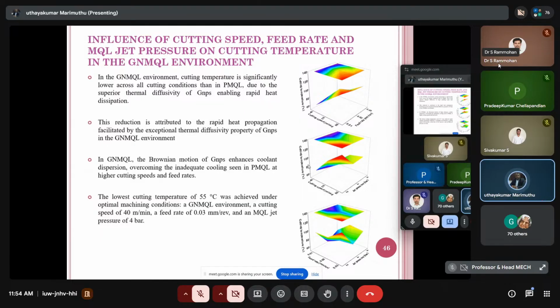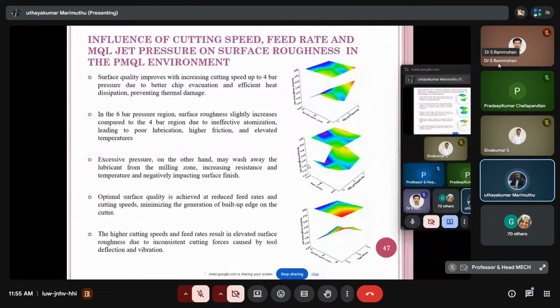The lowest cutting temperature of 55 degrees centigrade was achieved under optimal machining conditions: GNMQL environment, cutting speed 40, feed rate 0.03, and MQL jet pressure 4 bar. This is about the same for the surface roughness in the PMQL environment. So understand the concept: two different parameters we have taken as output responses. One is the cutting temperature, another is the surface roughness. Each one is described in a systematic way.